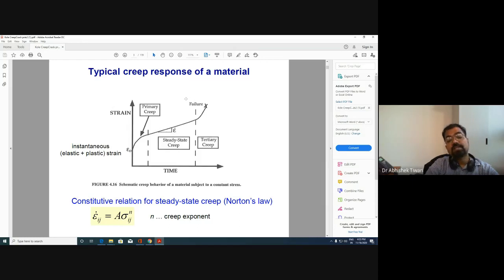If you increase the stress further, then you may skip the steady state part also, and the material simply deforms in tertiary creep. So it depends upon how much stress you have applied and what the temperature is. If you increase the temperature, again, the deformation will be very drastic. So we are talking about moderate temperatures.